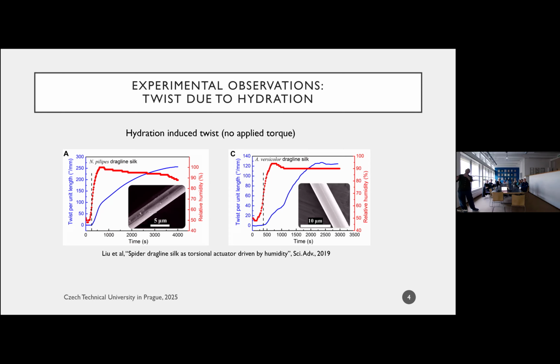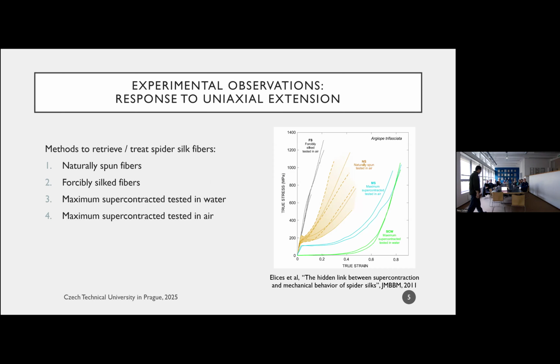This is the same result for spider silk fiber that was retrieved from a different spider species. Right. So this happens to different degrees, to different extents, but it happens to most of these silk fibers. Okay. And if we're going to talk about fibers, we should also talk about their mechanical response. Practically the only thing you can do with a fiber is stretch it uniaxially, right? And so what you see here is the stress strain curves of the spider silk fibers.